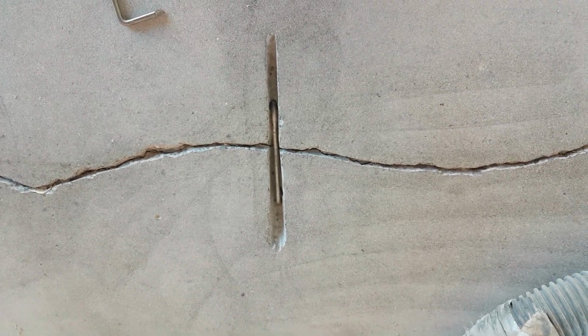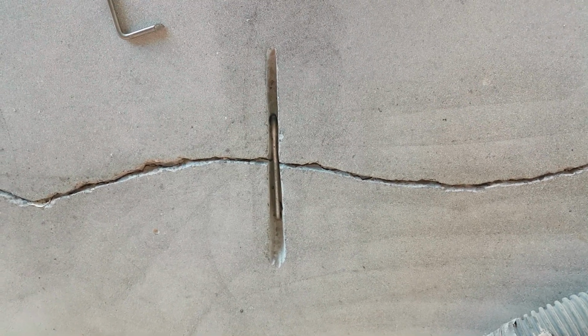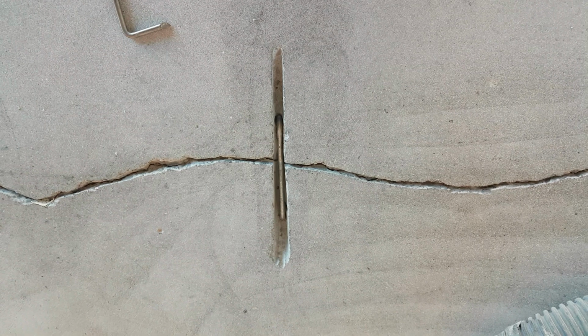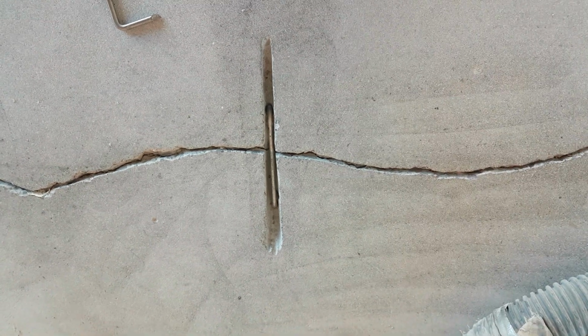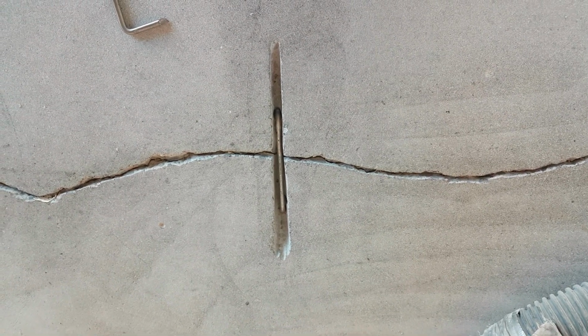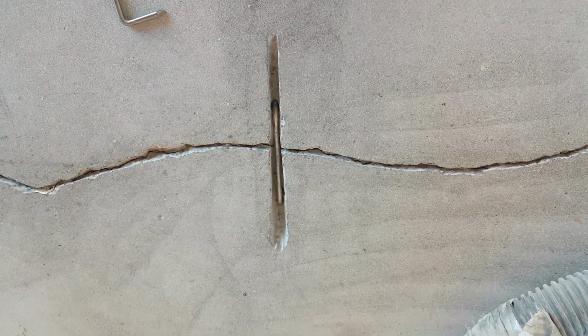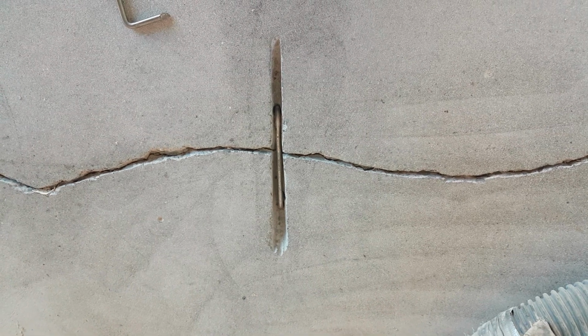The fast fix, being a really thin product, will get quite deep into that. We reckon on average probably around about 30 to 40 millimeters, but you've still got the rest of that slab that's got the crack, and if there's excessive force put back on it, that weakness will act as a starter, and then we'll find the weakest point around that to come back through again.